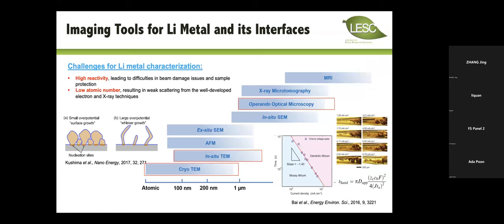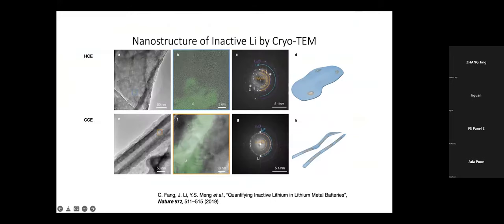Now, lithium metal characterization is particularly challenging because of the high reactivity of the lithium. In fact, in the vacuum, you have a lot of reactivity of the lithium, even in the high vacuums like SEM, FIB. Now, the low atomic number makes it quite difficult, but with the cryo-EM, Stanford team has shown you can get a very nice BCC structure of the lithium metal.